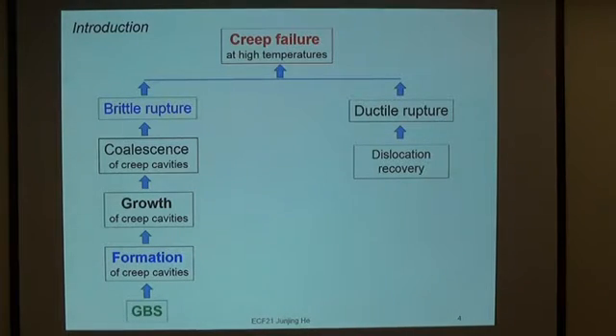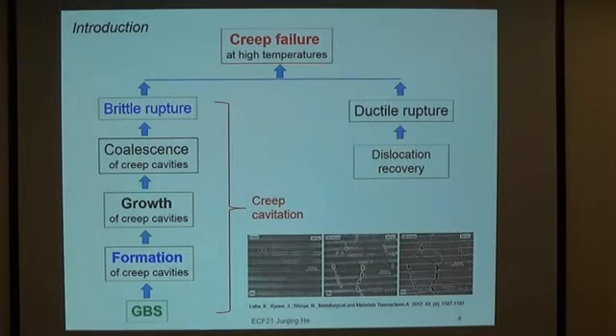In general, creep failure can proceed in two modes: brittle rupture and ductile rupture. For ductile rupture, the main mechanism is dislocation recovery. And brittle rupture is due to creep cavitation, which can result from the formation, growth, and coalescence of creep cavities at grain boundaries.